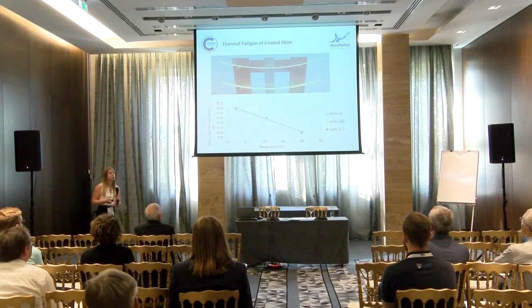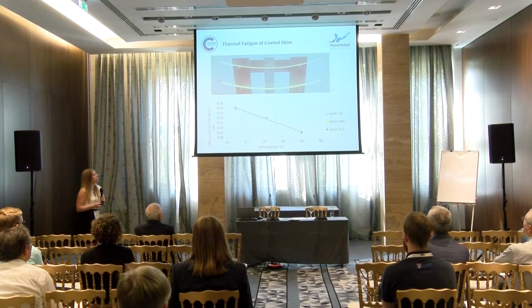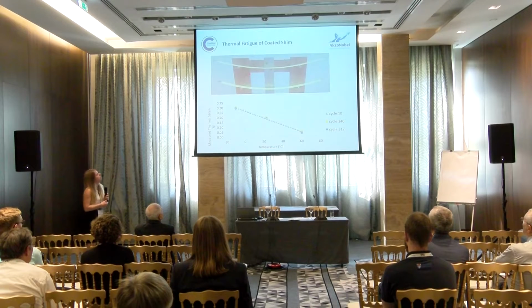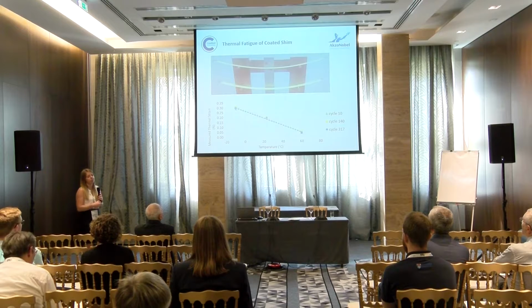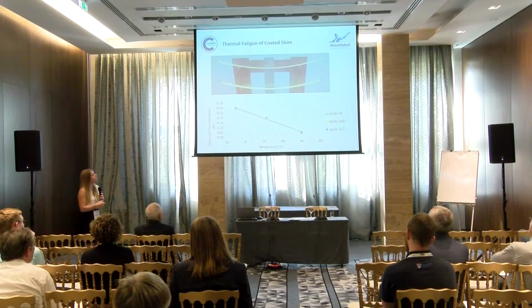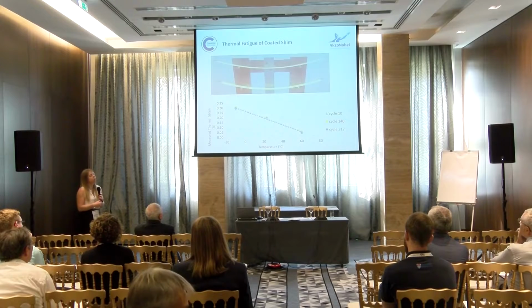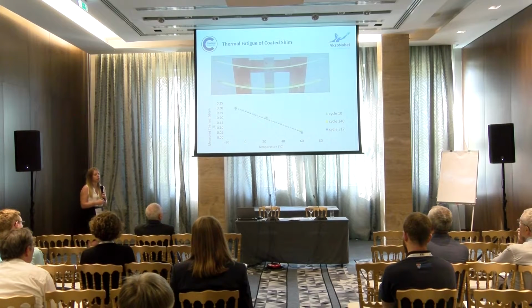So in order to understand what levels of thermal strain might be happening within the coating, this bimaterial strip method based on an ASTM standard was introduced. So this involves a coating applied to a thin shim, which was placed within the chamber along with the T-sections. As the coating contracts, the shim will deflect, and this deflection from linearity can be measured and translated into a thermal strain.